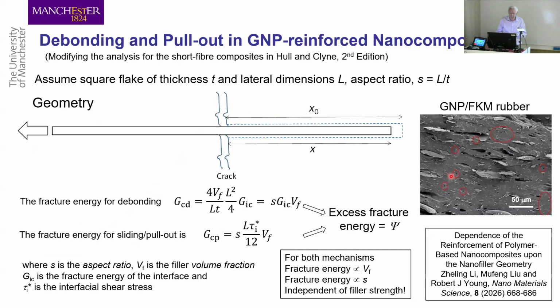So let's look now at fracture of these materials. And I want to just go through failure of the materials. And that turns out to be quite interesting and also related back to conventional composite mechanics. If you look at a fracture surface here of a torn graphene reinforced rubber, you see all these pulled out flakes. You can see the pulled out flakes.